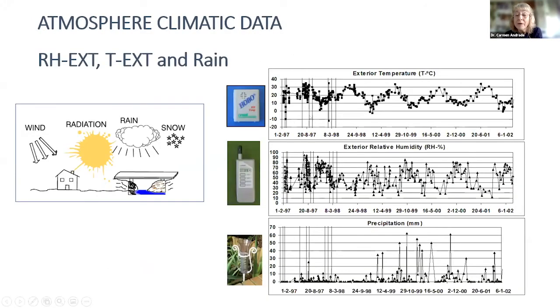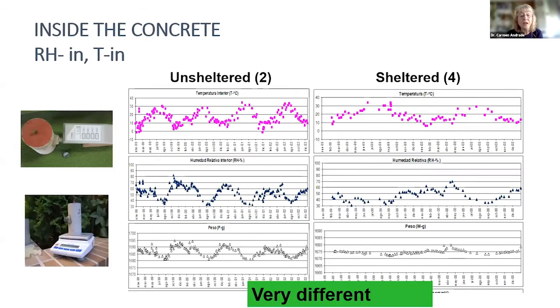This is a summary of 2 years of record. Now we have a much longer record, and we were measuring in the atmosphere the temperature, the relative humidity, and also the raining regimes, which we notice is a very key parameter for the relative humidity inside, the amount of rain that is just fed into the concrete.